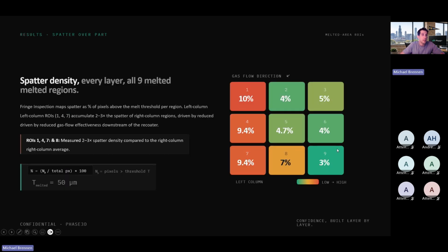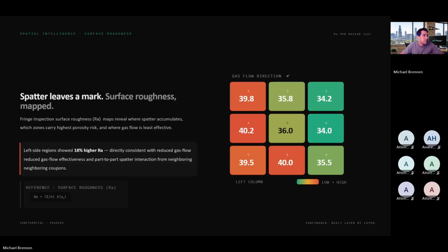So again, we see a really clear correlation that this bottom left region, where we build into the gas flow, we see an accumulation of spatter density on this lower left side, almost 2 to 3 times the spatter density when compared to the right column average. So clearly this aligns with the results that we saw earlier, where the bottom left corner of the powder area had a much higher spatter density. And we see this same trend for the surface roughness as well.